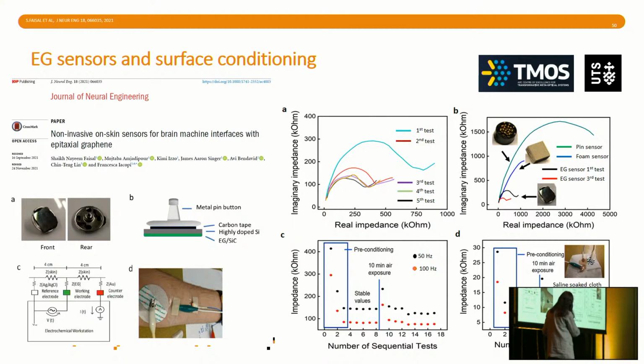This is a very, very simple system where we have just a square of that system, so graphene, silicon carbide on silicon. Remember that story of the interface. I won't be able to go into these details, but we know how to make that interface extremely leaky so that it's completely conductive. And so we use that condition, and that means that any signal collected on the top here will be transported throughout the silicon on the backside without any additional conductive path.